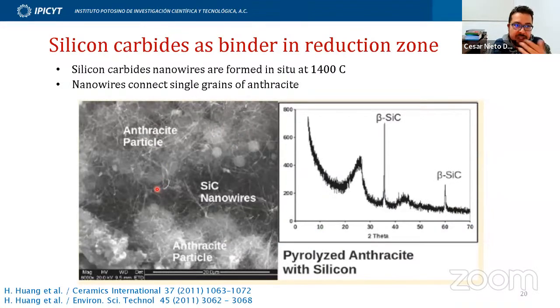And the third binder is the silicon carbides. Here is a SEM picture of the anthracite briquette after pyrolysis at 1400 C under nitrogen conditions, I guess. I don't remember very well, but you can see how all the carbon grains are connected by the silicon carbide nanowires.